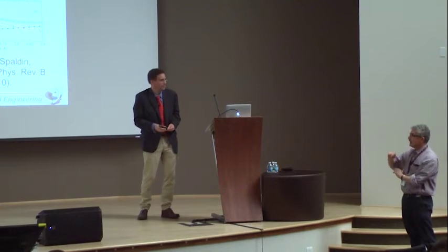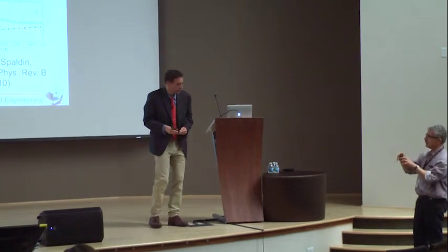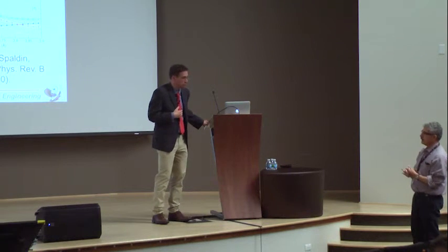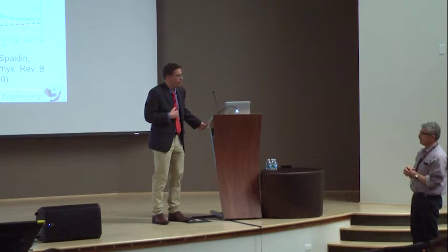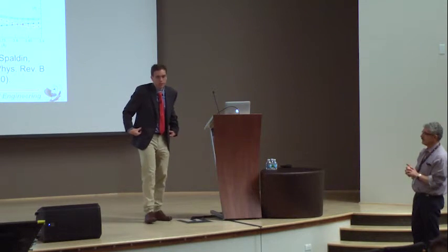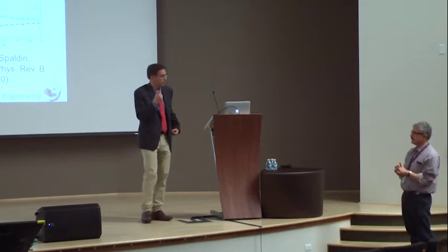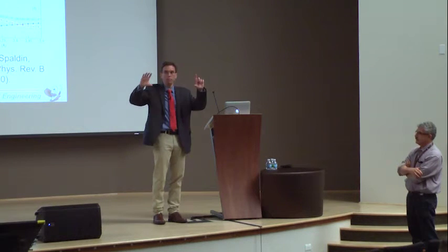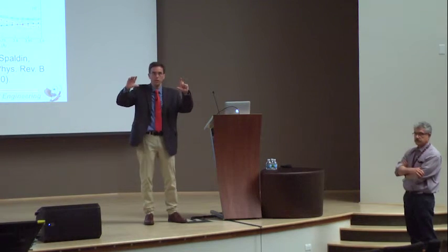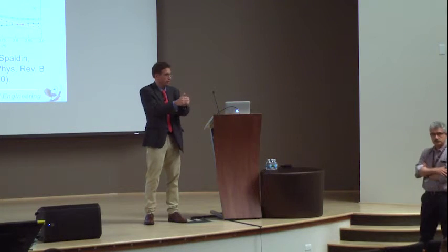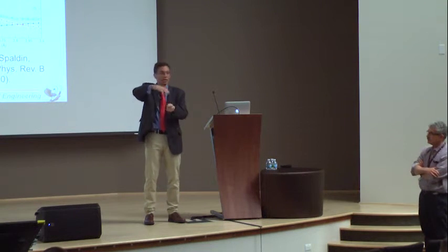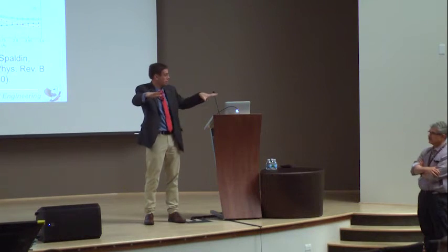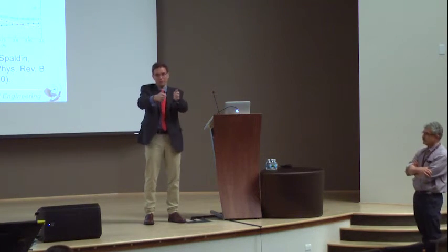I have a question, Paul. Yes. So you showed in the beginning the domain structure that has sort of a wiggly structure. So what drives the periodicity of structure? That is the same thing as you would think about driving the periodicity of the magnetic domain structures. What happens is that if you try to make something that has a uniform polarization, and very thin, then it has a tremendous shape anisotropy.